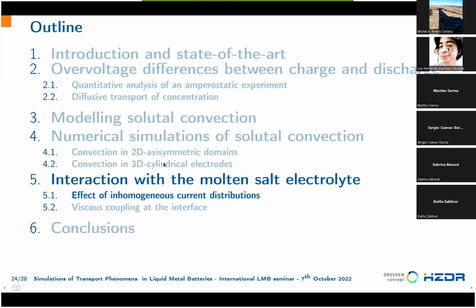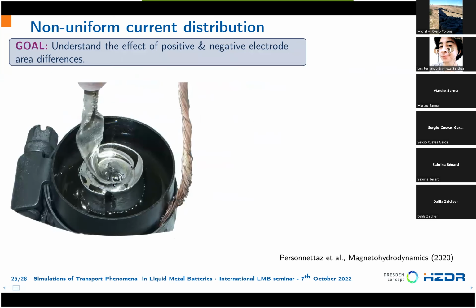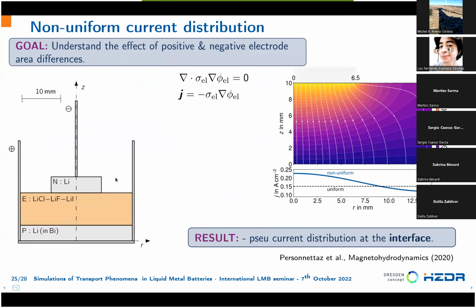So in the last part, we will study the interaction with the molten salt electrolyte, starting from electrical coupling. If we look at our experiment here, we see that the negative electrode has a smaller diameter than the positive electrode. So this means that we will not have really a uniform current distribution at this interface. And we can compute the current distribution inside the electrolyte. So now we focus on the electrolyte, just solving the Laplace equation for the electric potential.